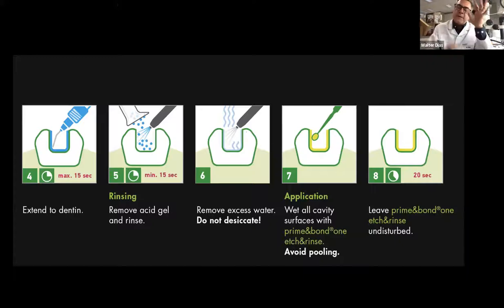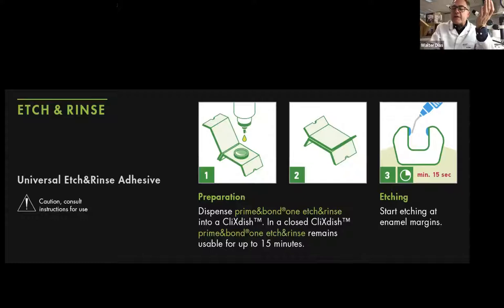But wait a minute, what you're doing is you're etching the dentin, you're etching the enamel, you're etching the sclerotic dentin, the hypermineralized dentin. And what they mean here is that you should start etching the enamel margins and the sclerotic dentin and the hypermineralized dentin later. So the enamel is etched at least 15 seconds. What I'm trying to say is don't be afraid to etch the enamel. You should, instead of under etching, always over etch it more than 15 seconds.